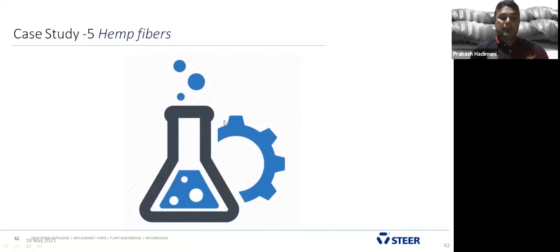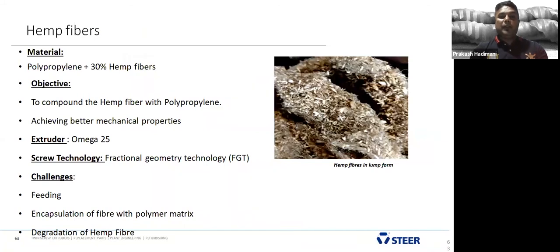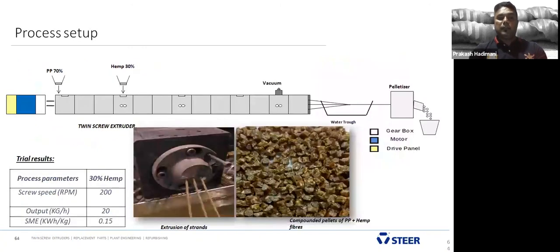Okay, finally the last and fifth case study, we are going with hemp. Hemp again has higher moisture content and forms lumps, and feeding is again a big challenge with hemp powder. And we could manage 30% feeding with the polypropylene. And these were the pellets, with 30% hemp using the same Omega 70 and 30 combination, feeding hemp from the side feeder, and we could manage better dispersion, but we are still trying to test the mechanical properties, not completed yet. Our next level is to understand the mechanical properties.